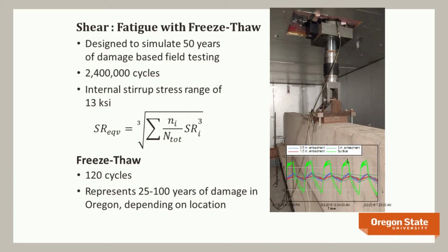At the same time it's bouncing up and down, we're also freezing and thawing it. And in Oregon, we have a pretty broad range of environmental conditions. And so we've got 120 freeze-thaw cycles happening simultaneously with those fatigue cycles. And we can say that those 120 cycles represent anywhere between 25 and 100 years of service life, depending on where in our state you are.